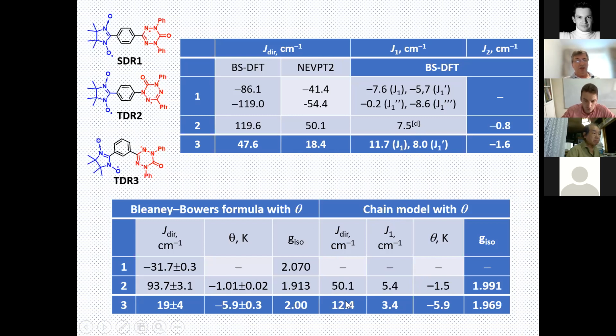And using this model for radical 2, we revealed ferromagnetic intramolecular exchange interaction of more than 50 inverse centimeters, and inter-radical exchange interaction near 5 inverse centimeters. For radical 3, we have a little bit smaller intramolecular and inter-radical exchange interaction, but anyway, all of them have positive values.